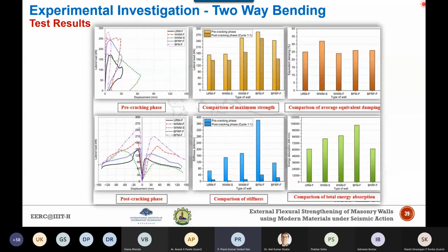So all the tested walls in the post-cracking phase also have shown a very large deformation capacity before the incipient collapse. This is indicative of a significant energy dissipation capacity, which is a very important and desirable characteristic with regards to seismic resistance. And here you can also see that the degradation in strength up to 37% has been observed in the initial cycle, which has become relatively gradual during the post-cracking phase.